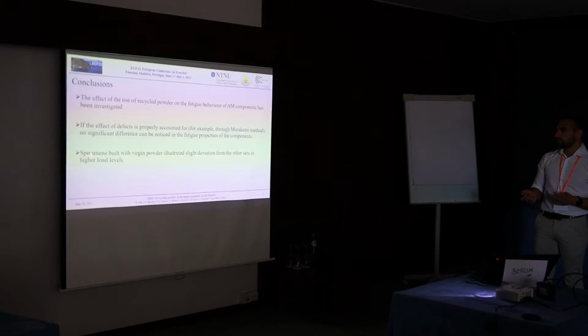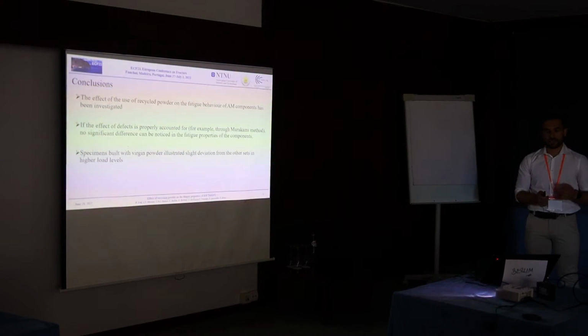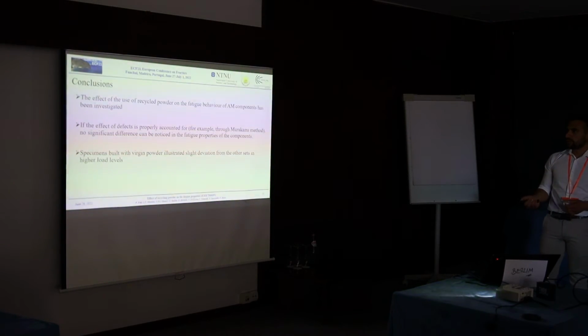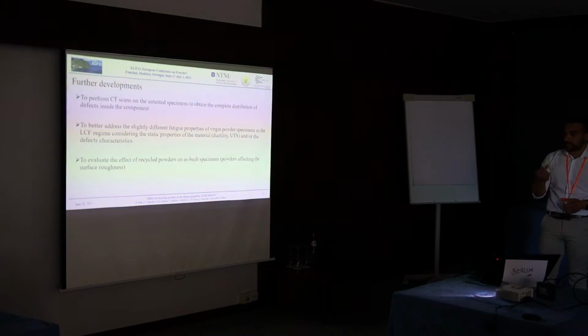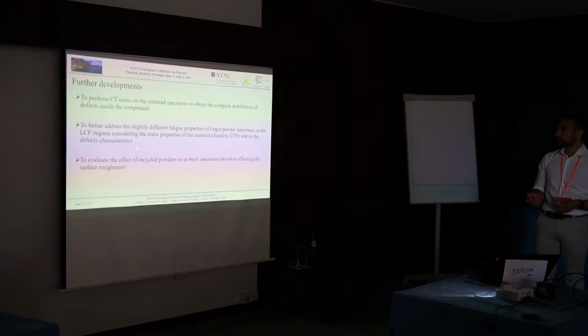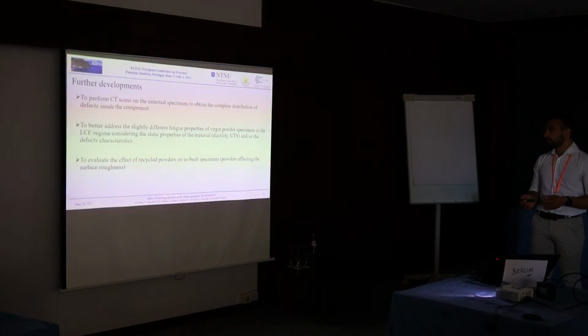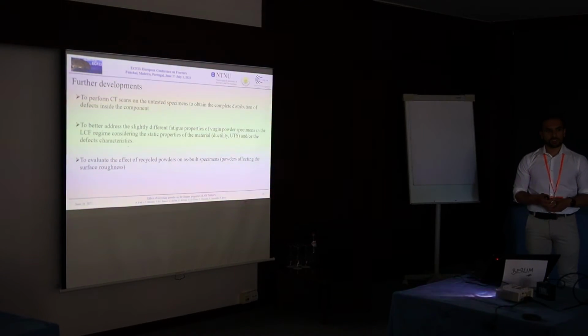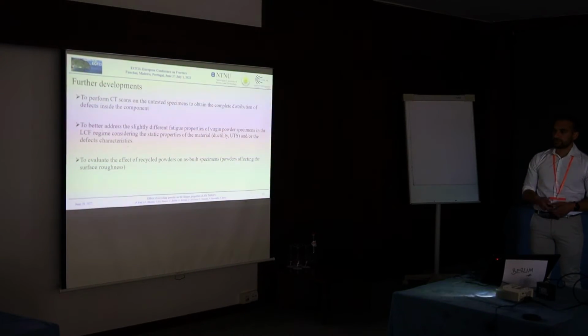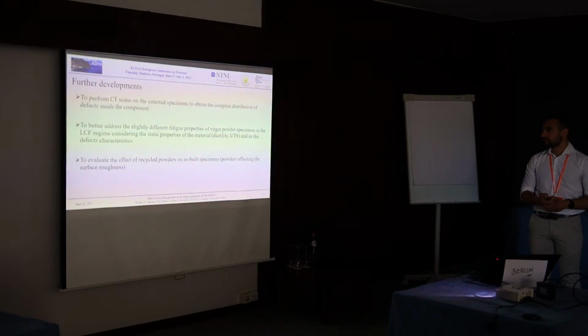But we also wanted to point out that the specimens built with virgin powder illustrate this slight deviation from the other sets at the higher load levels, that we are thinking to further investigate, maybe also trying to correlate this deviation to the static properties of the material, such as the ductility or UTS, and/or to the different defect characteristics. Another further development that we are thinking about is to have a CT scan of all the specimens in order to have the complete distribution of the defects inside the component, and to have a better overview of the defect morphologies inside this kind of components.